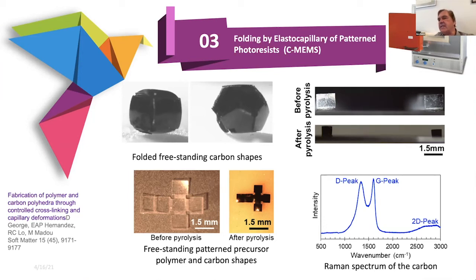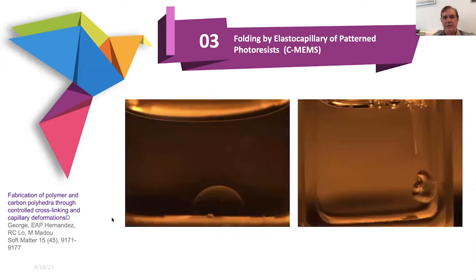And by the way, this is a typical furnace we use to convert these polymer shapes into carbon. This is a furnace that we either completely fill with nitrogen or another inert gas, flowing inert gas during the pyrolysis cycle. By the way, the temperature cycling is extremely important. How fast you heat, how long you stay at each point when gases escape the polymer precursor, and etc. It is somewhat of an art form. So let me show you two videos.